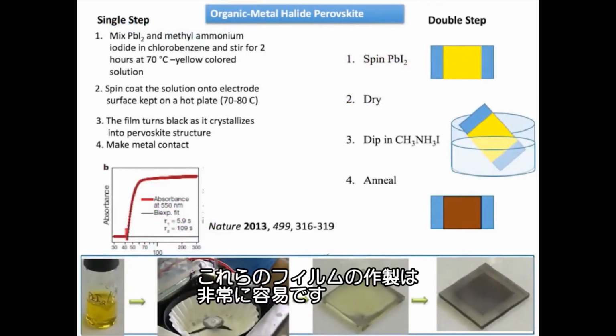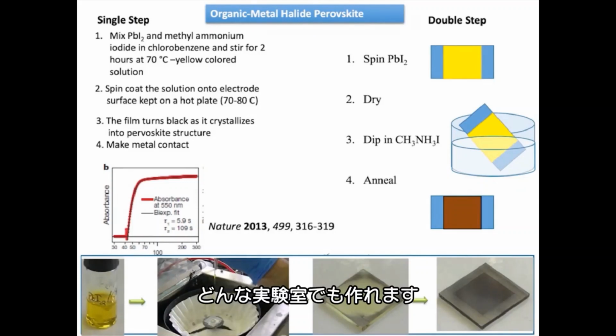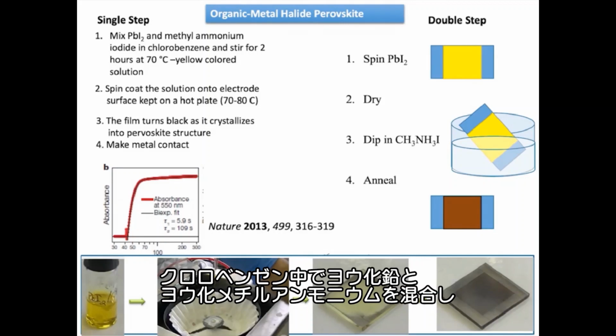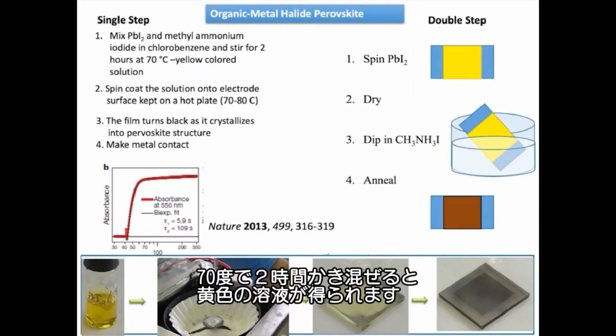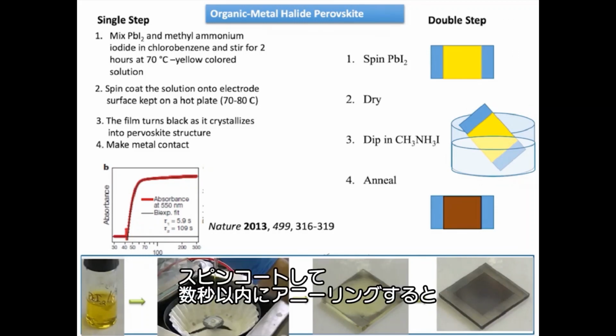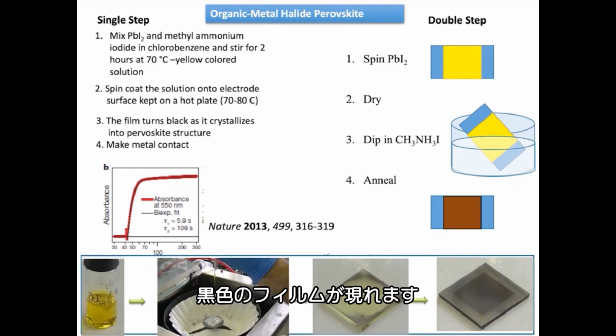How do you make these films? And it is very simple. One can make it in any lab. You mix lead iodide and methyl ammonium iodide in chlorobenzene and stir for 2 hours at 70 degrees, and you get a yellow colored solution. Spin coat it and then anneal it. Within seconds you will see this black colored film, and the steps are shown at the bottom, showing how the color change occurs.